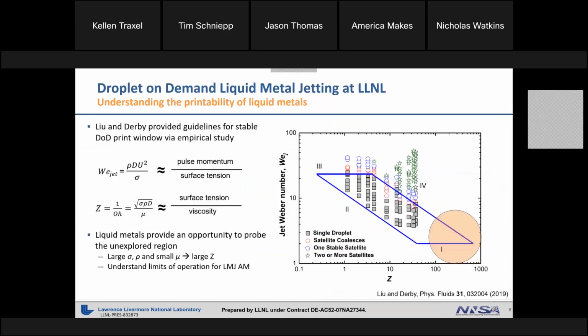Higher Z means the more likely the ejections will create unwanted satellites for a given jet Weber number, as shown in the downward trend of the window. These satellites may diminish part quality by reducing resolution and density. Notice how the window predicts that no satellite-free droplets could be printed beyond a Z of around 700. So we tested this limit using liquid metals because their unique characteristics place them in the high Z region, as shown by the orange circle.